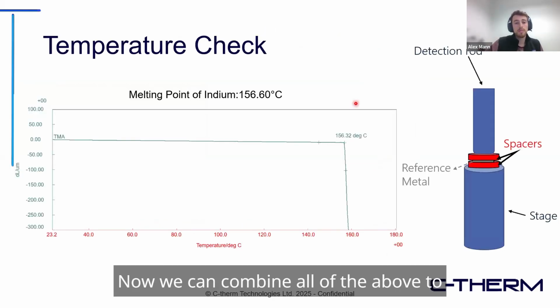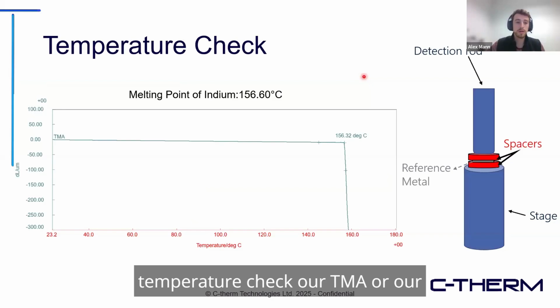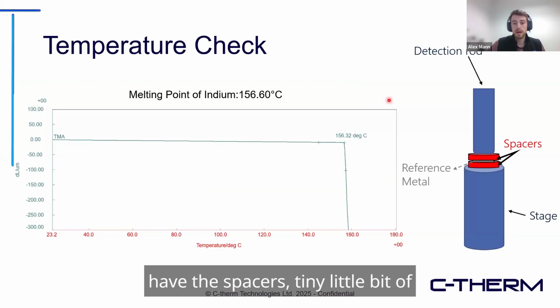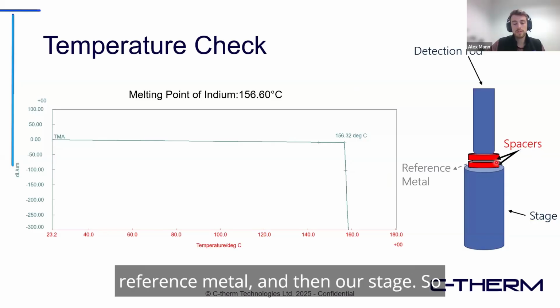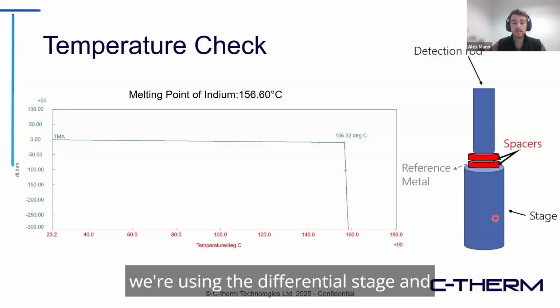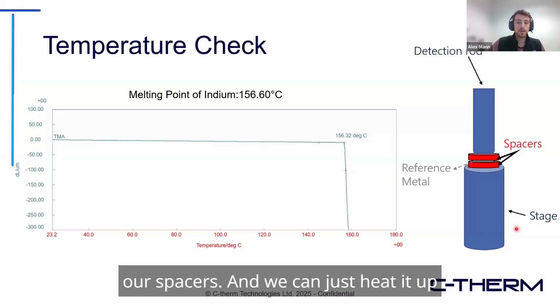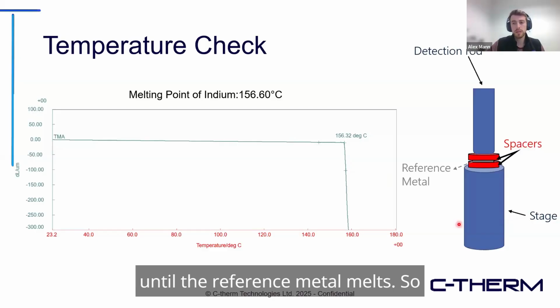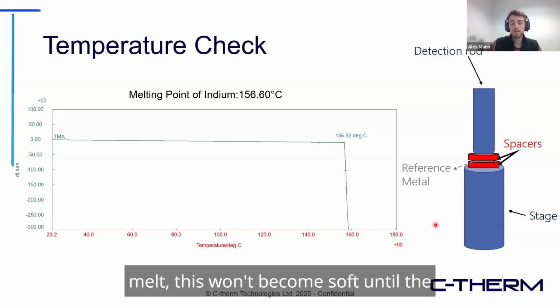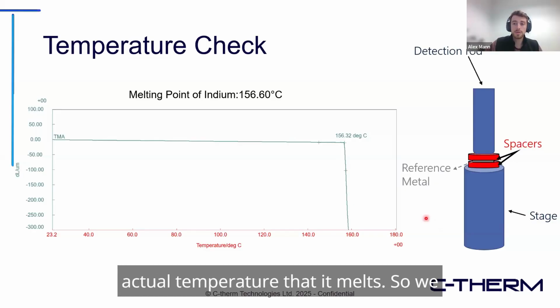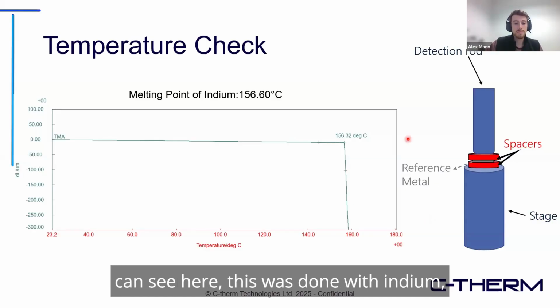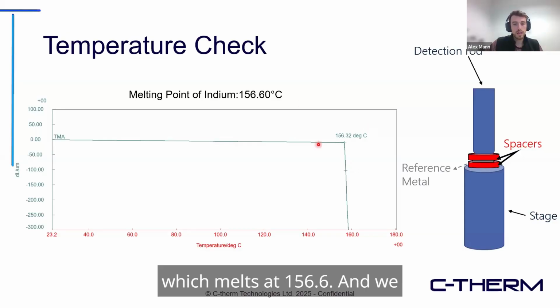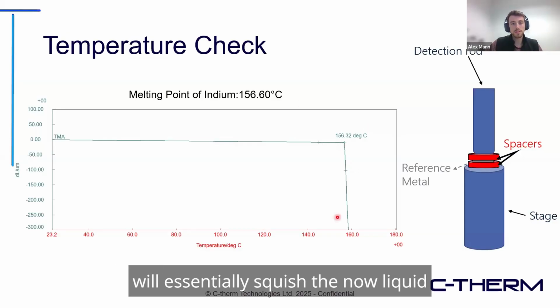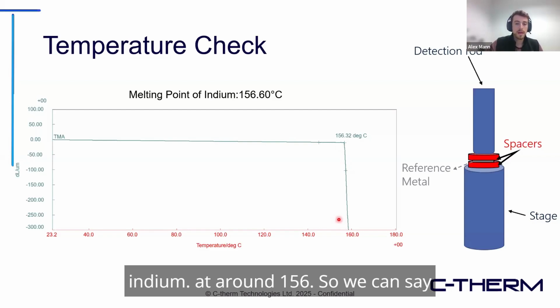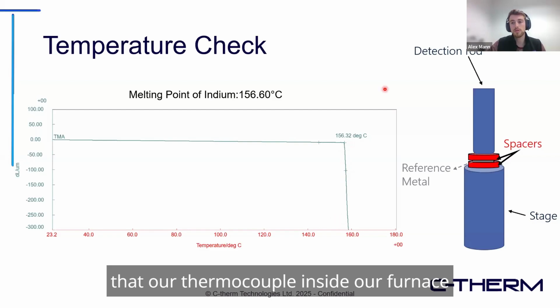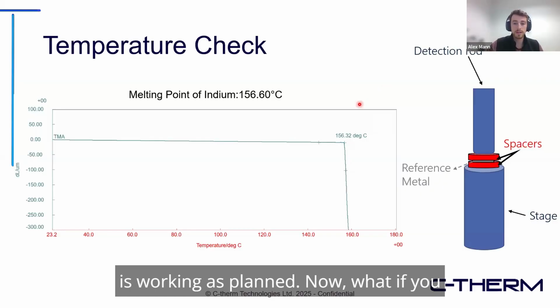Now, we can combine all the above to temperature check our TMA or our thermocouple. So what we can do is have the spacers, a tiny little bit of reference metal, and then our stage. So we're using the differential stage and our spacers. And we can just heat it up until the reference metal melts. Because it's crystalline with a very sharp melt, this won't become soft until the actual temperature that it melts. So we can see here this was done with indium, which melts at 156.6. And we saw the big drop. This is where our rod will essentially squish the now liquid indium at around 156. So we can say that our thermocouple inside our furnace is working as planned.